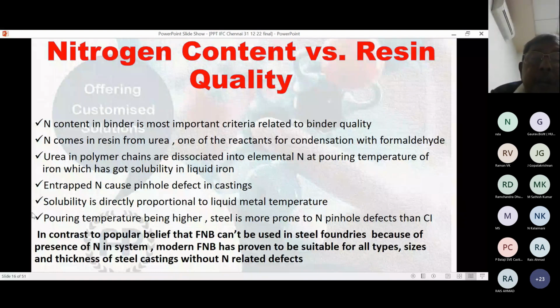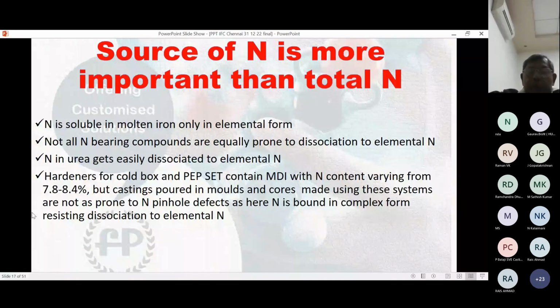In contrast to popular belief that furan cannot be used in steel foundries because of presence of nitrogen in the system, modern furan has proven to be suitable for all types, sizes, and thickness of steel castings without nitrogen-related defects. Source of nitrogen is more important than total nitrogen. We have already discussed that nitrogen in elemental form is soluble in the metal, not in molecular form. So all nitrogen bearing components are not equally prone to dissociation to elemental nitrogen. Nitrogen in urea gets easily dissociated.